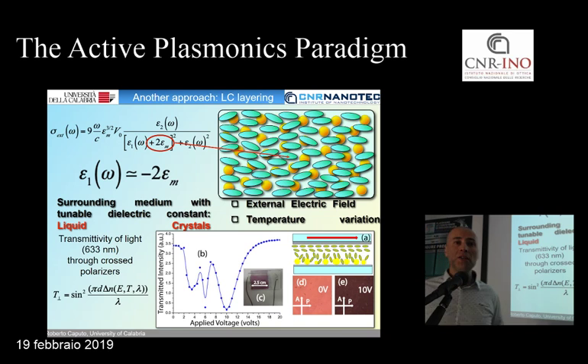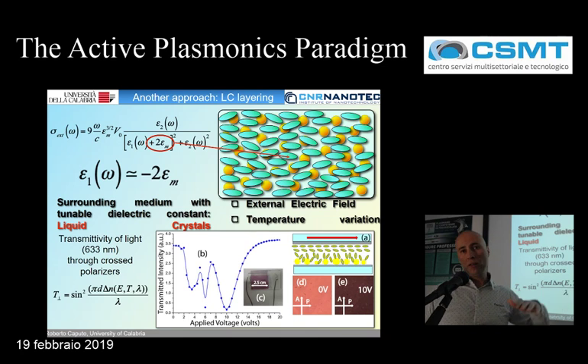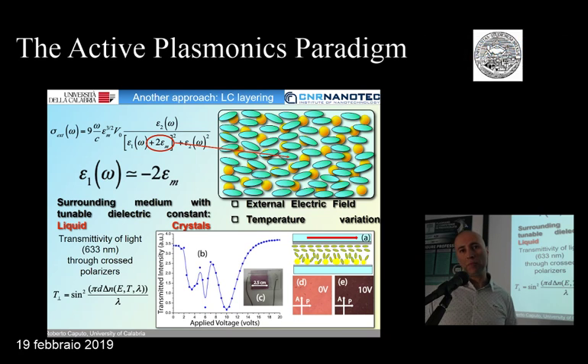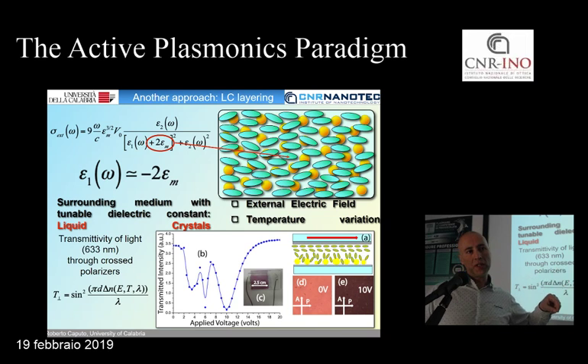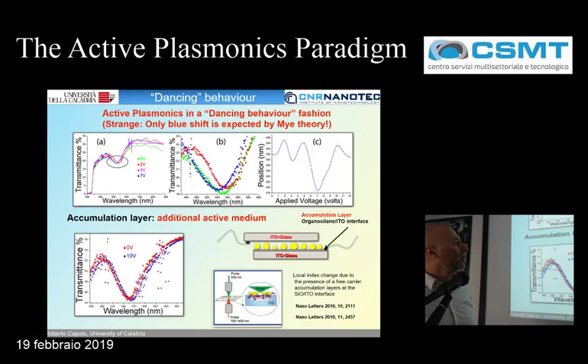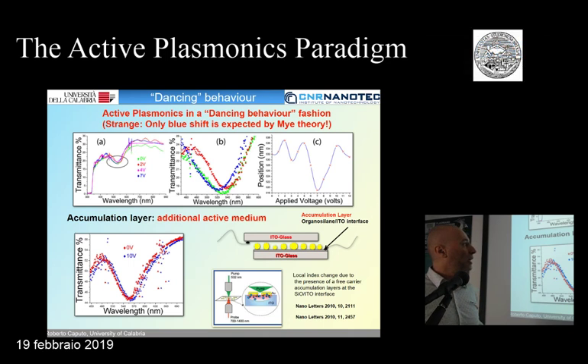Another approach was just to fix the nanoparticles on a substrate and layer the substrate with the liquid crystals. So in principle, we changed the approach in a noticeable way, because in the previous attempt, the liquid crystals condensed the nanoparticles. In this case, the nanoparticles are fixed to the substrate, and you can layer it with liquid crystals. So, in a few words, what happens is that you can also in this way actively modify the resonance position by applying an external field.